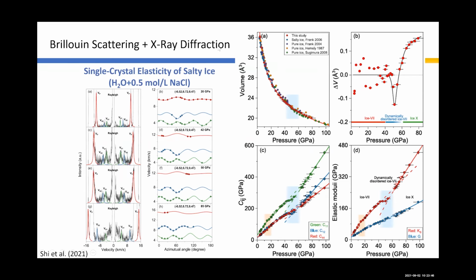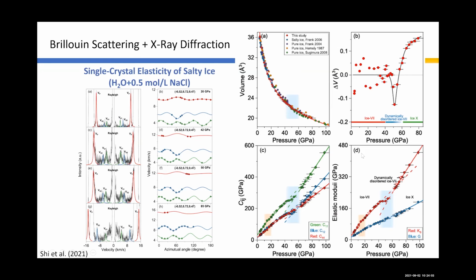From this work, the interesting thing is that we go from ice VII. Look at the right panel, panel C and panel D, that is a single crystal. We can see that when we go from ice VII to the dynamic disordered ice VII, there is an anomalous drop in the C11 and the C12. And the C44 actually is not affected strongly. It's only weakly affected by this transition from ice VII to the dynamic disordered ice VII.